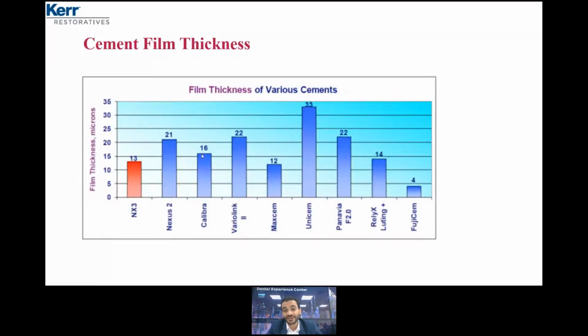And for film thickness, on the left side, you can find NX3 at almost 13 micron as a film thickness, in comparison with other cements. But maybe you will say you have a cement with only 4 micron film thickness. Yes, but it's a glass ionomer. It's not a resin cement. It's not a composite cement.